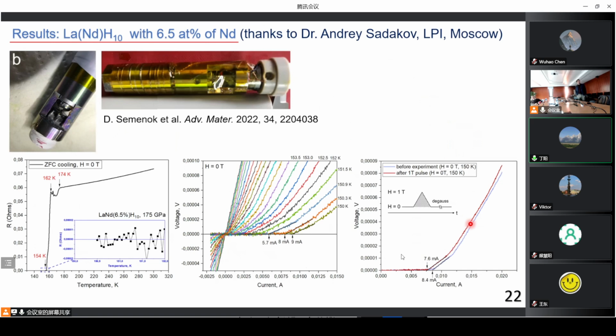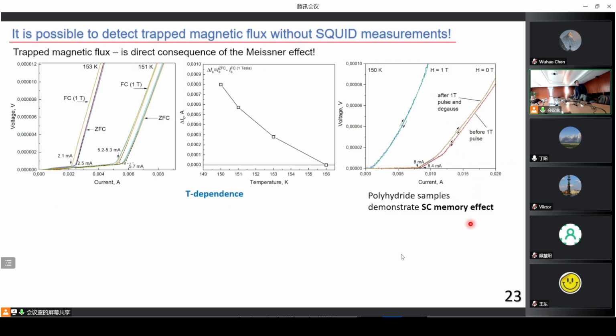So you see this hysteresis loop here. Exactly. This is a unique, conclusive measurement for the Meissner effect. Is there any other possible reason for this kind of hysteresis? Of course, we didn't analyze in detail what the possible reason is, but we were able to repeat this measurement.